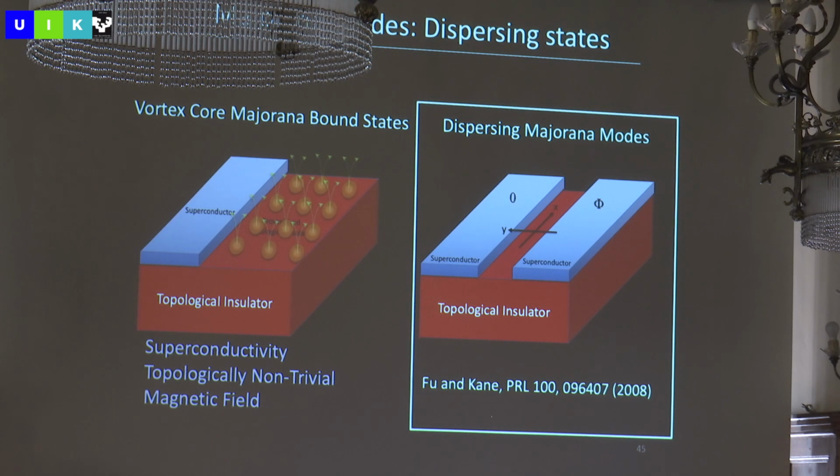But in this system, because of the parameters that we have, which is delta and EF, the Caroli-de Gennes-Matricon states are actually quite well separated from the Fermi energy, 100 microvolts. This allows you to resolve that state at zero bias very clearly just by itself, right?